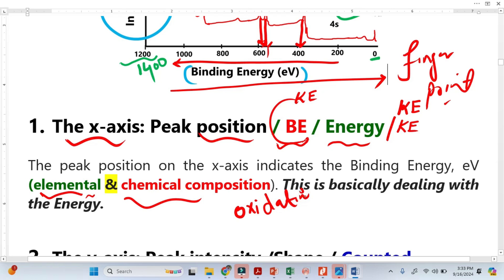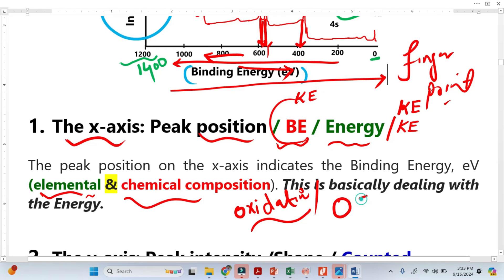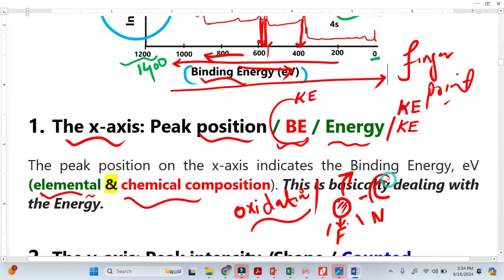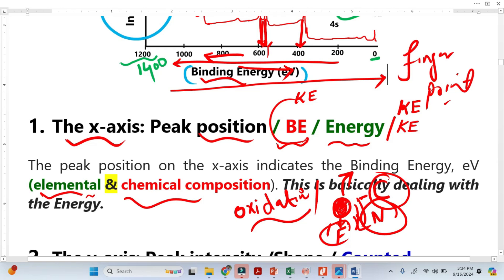Beyond qualitative identification, we can also determine the oxidation state of the elements. When a peak shifts toward the left or right, the oxidation state is increasing or decreasing. We can also identify the chemical environment — whether oxygen is bonded to carbon, nitrogen, or fluorine. The oxidation state changes because of electronegativity: if a neighboring element has higher electronegativity, it pulls more electrons from the oxygen, making it electron-deficient. The remaining electrons are attracted more toward the nucleus, binding energy increases, and we see the peak shift toward higher binding energy.